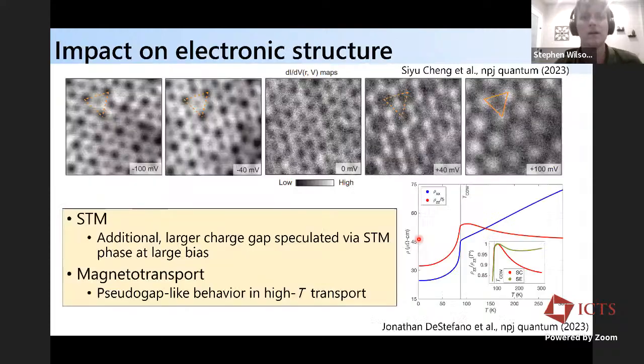And so the last thing I would highlight is that this diffuse scattering at high temperature, these short-range Ising-like correlations, seemingly impact the electronic properties. There's a high temperature pseudo-gap-like behavior that's reported in the system, as well as a larger charge gap that seems to be picked up in STM. And so potentially these two things are coupled.